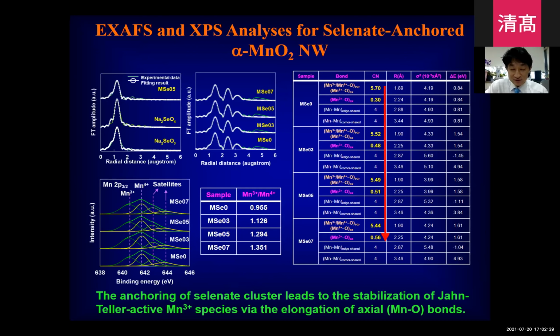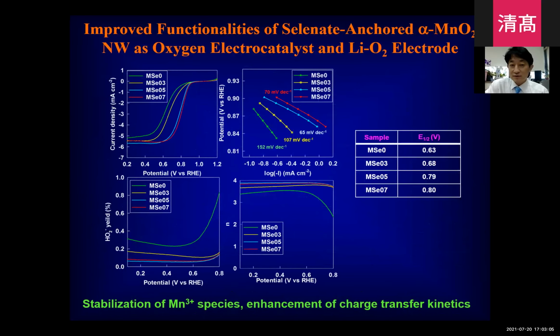As you can see here, as the selenium content increases, we observe the increase of the coordination number of the axial manganese 3+ oxygen shell. So it's the evidence for the stabilization of the Jahn-Teller active manganese 3+ species. It is further confirmed by the XAS analysis, as you can see here. So we apply those materials as ORR catalyst.